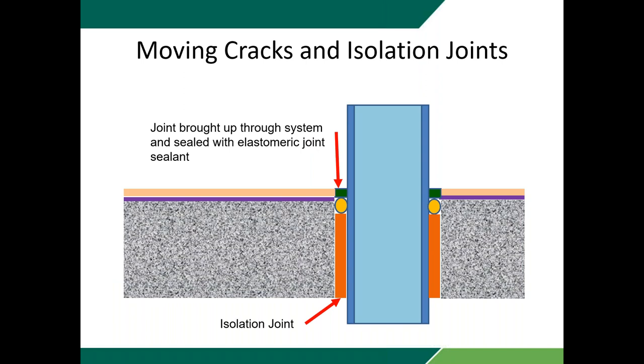In cases where we've got joints that want to move, such as isolation joints or maybe even moving cracks, those have to be transferred up through the system. The system can move, but it can't move that much. So what we end up doing is we transfer that up. In this case, we've got a penetration through the slab, and we actually put in an elastomeric sealant around the joint or in the joint to actually seal it where it's coming up through.